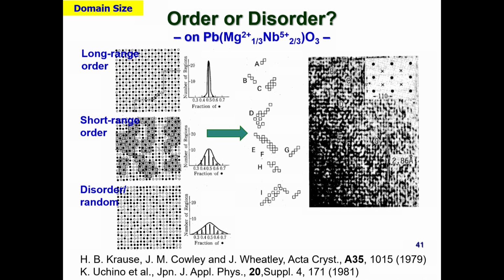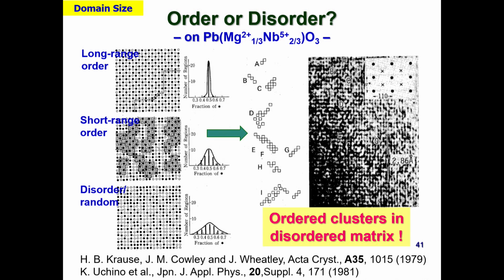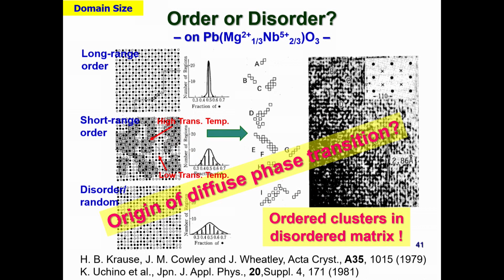So, practically using the electron microscope, the Krause group really beautifully shows the ordered cluster here, okay? So ordered cluster in this disordered matrix, this is the situation. So if you believe this ordered structure has a higher transition temperature, and this disordered part has a lower transition temperature, and this is a really wide range, this may be the origin of the diffuse phase transition, okay?